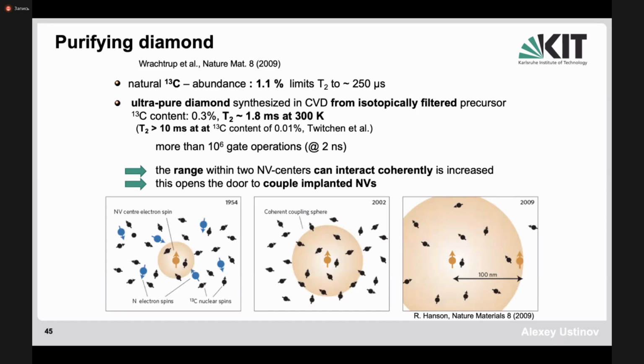Now, if one makes ultra-pure diamond, which can be synthesized from isotopically purified carbon, then the dephasing times increase at room temperature from a fraction of a millisecond to several milliseconds. And if one purifies more and more, of course, this time increases further to tens of milliseconds and more. And this already would allow millions of gate operations, because the gates can be applied very quickly, over a time of almost a nanosecond.